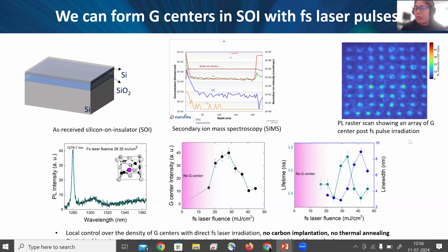Just as a proof of concept, we started out with just as-received SOI. We didn't do any ion implantation in this case. This SOI was basically from storage. We had this wafer for 10 years in our lab, and we first checked how much carbon, hydrogen, and oxygen, these hydrocarbons, are there in the wafer just from the storage.